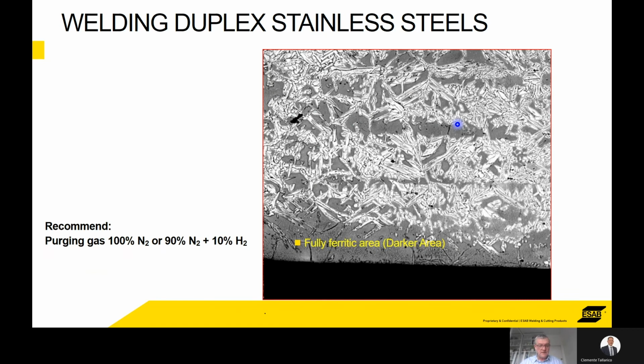Similarly, in the purging gas, same effect. If you don't replace the nitrogen by having a lot of nitrogen in the purge, then you're going to get these fully ferritic areas. So again, you've got a range here that is basically ferrite, not duplex. So you don't have the strength, you don't have the corrosion resistant properties.